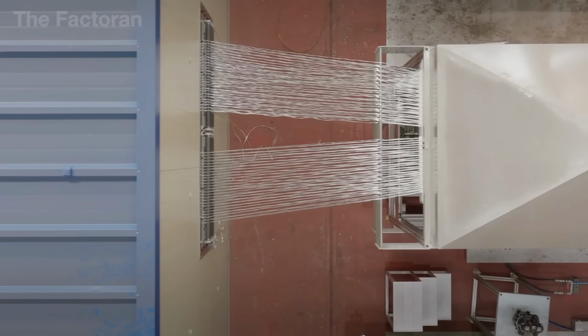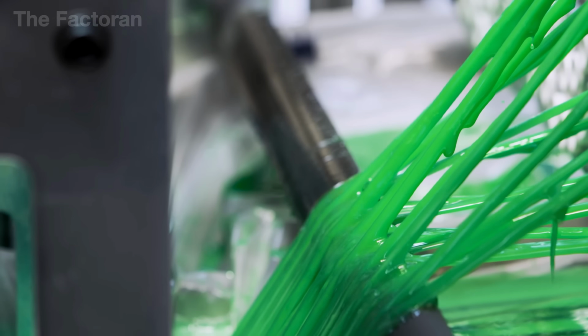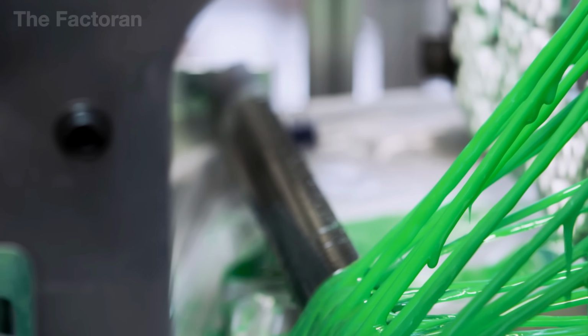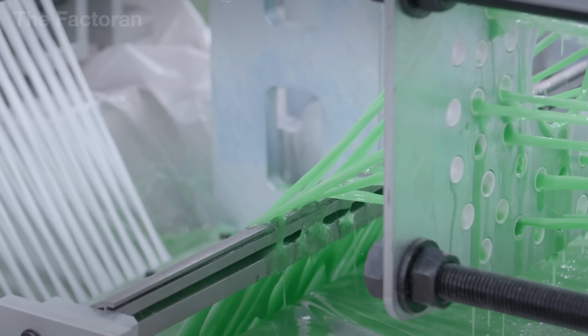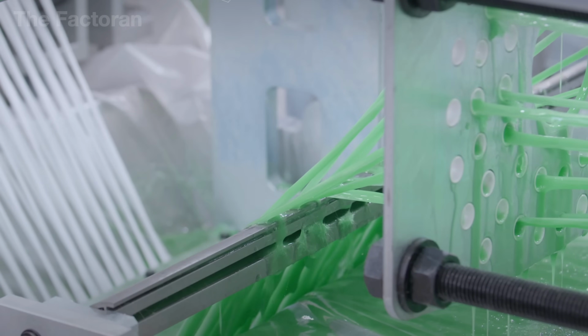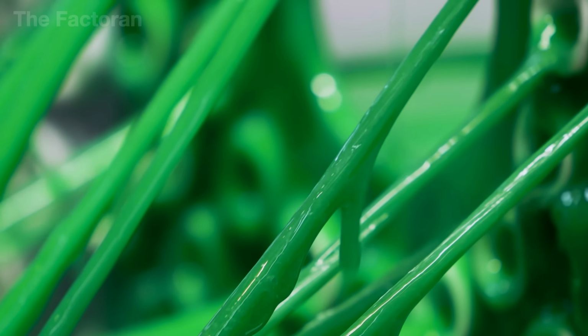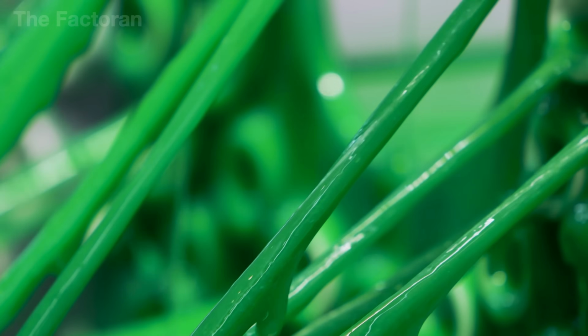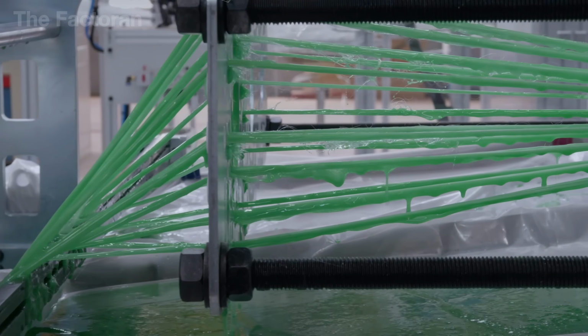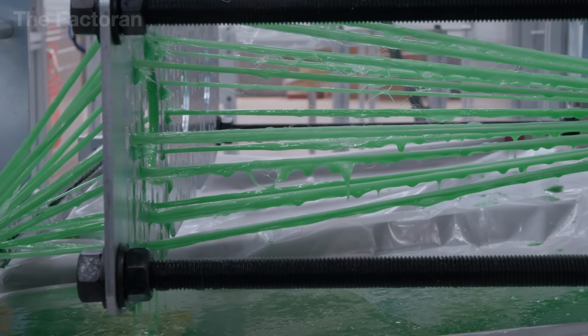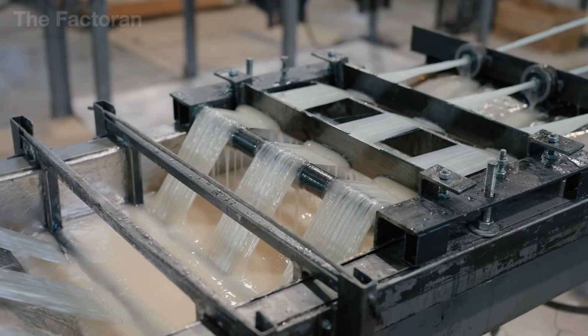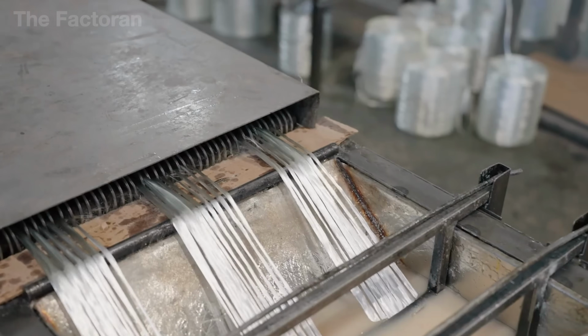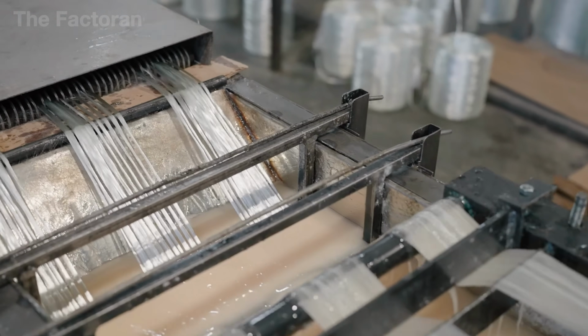The resin penetrates deep into each strand, both protecting the surface and bonding them tightly together. This step transforms loose glass fibers into a unified mass, ready to be shaped. The degree of resin penetration directly determines the strength and lifespan of the finished rebar. The resin infused into the glass fibers can come in many different colors, ranging from bright green to milky white.